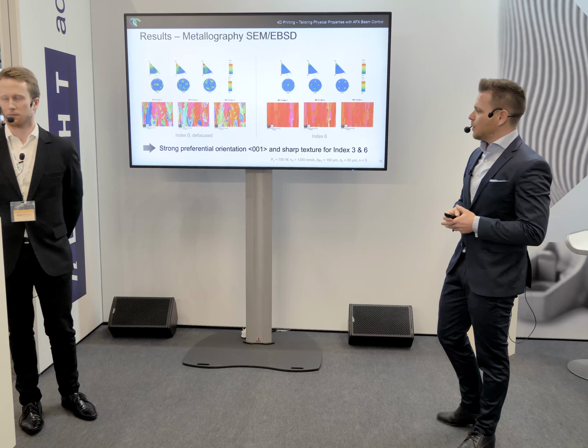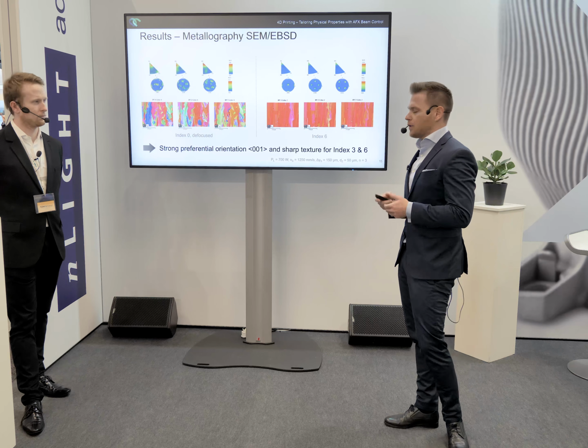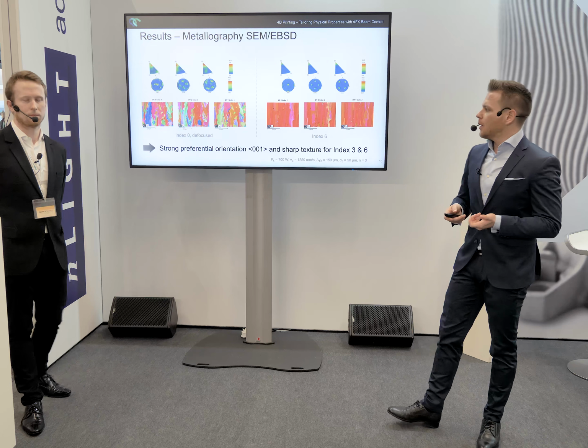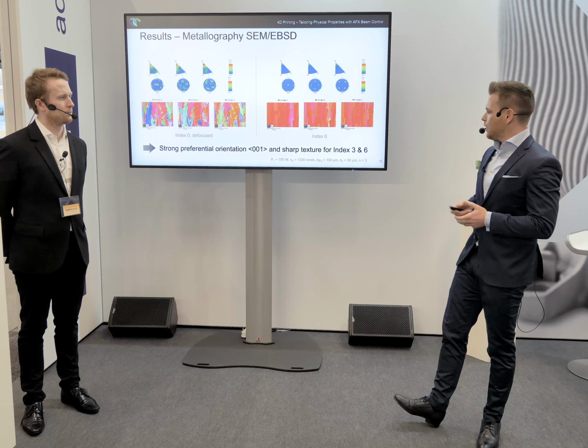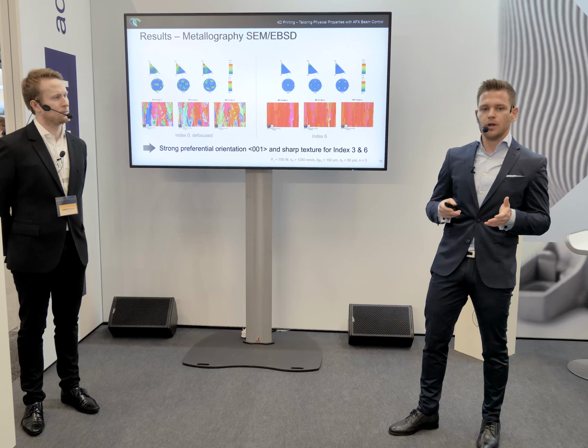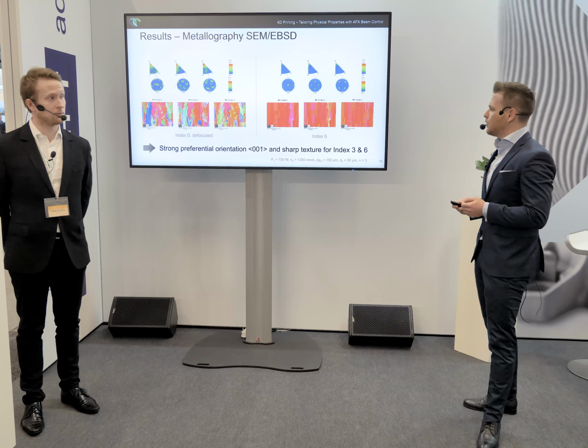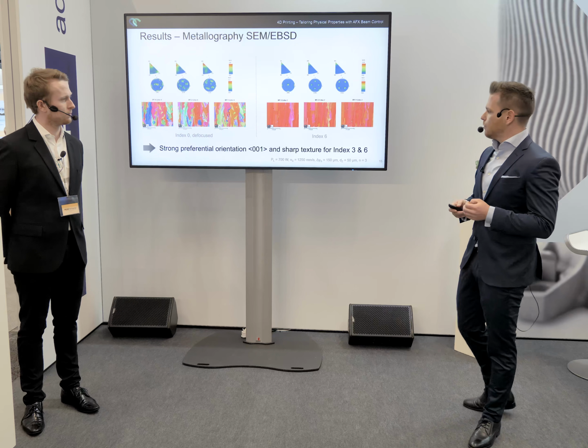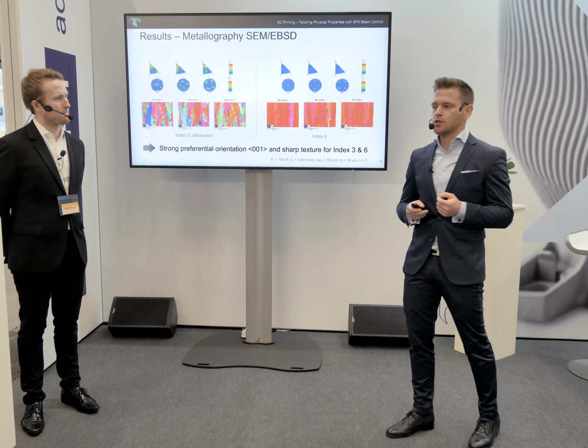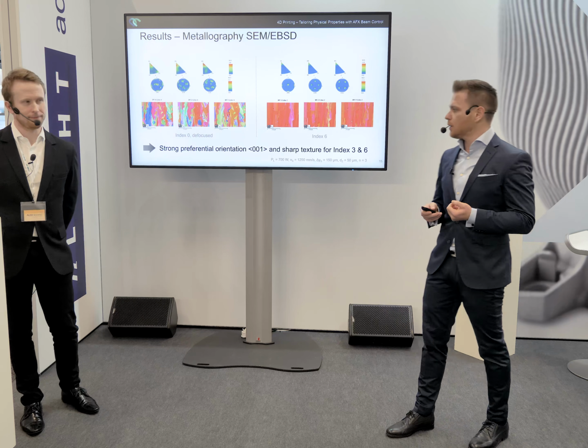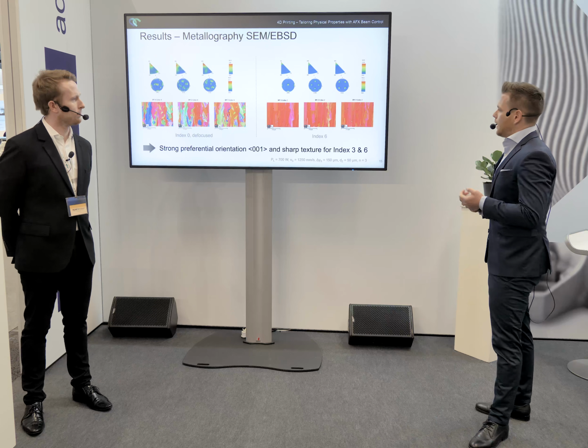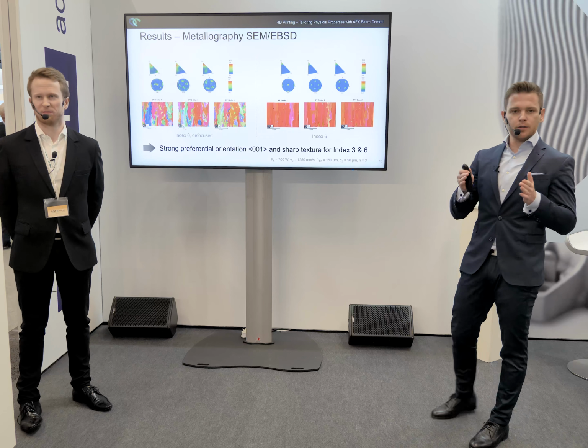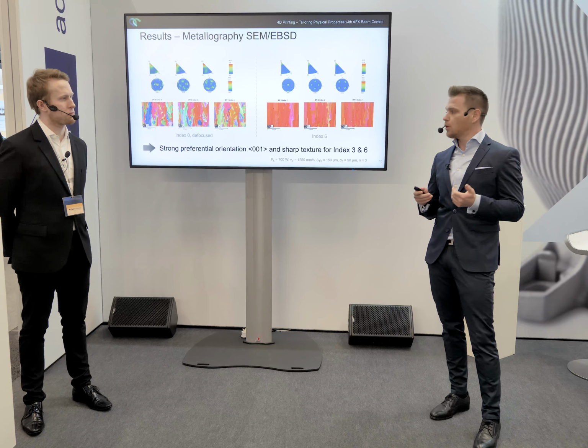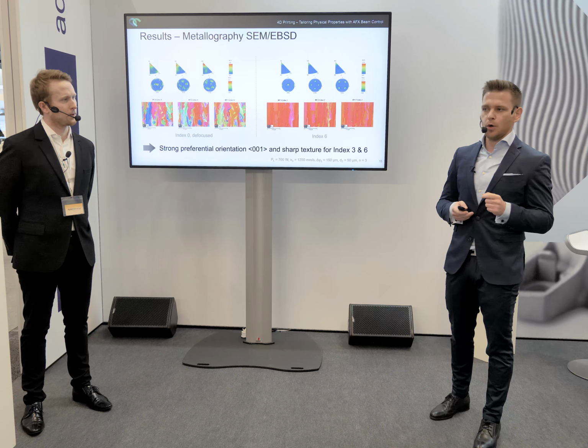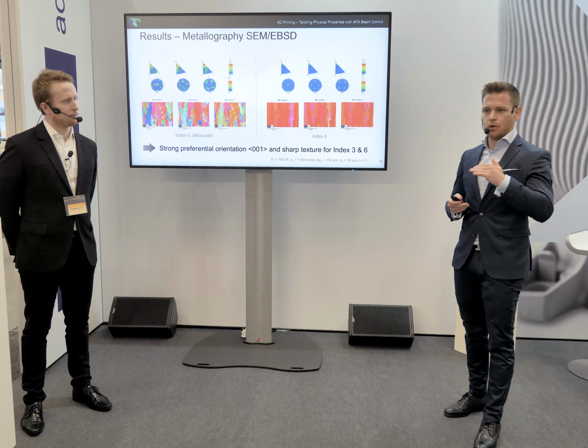On the left side we have the sample of index 0 with different grain orientations, while on the right side we have the sample of index 6 with straight columnar elongated grains parallel to the build direction. And this texture may help us to explain the differing mechanical properties. Having more elongated grains parallel to the build, and in our case also the load direction, means fewer perpendicular grain boundaries to the load direction.